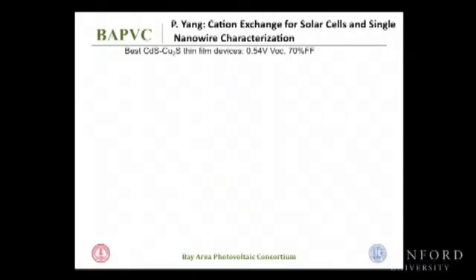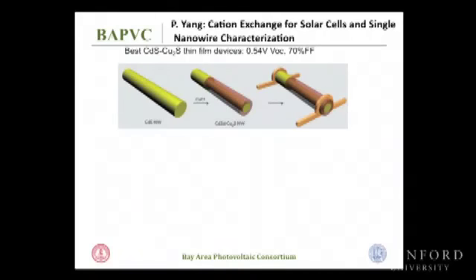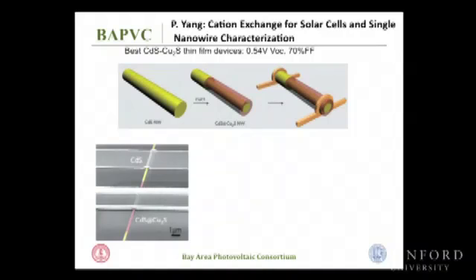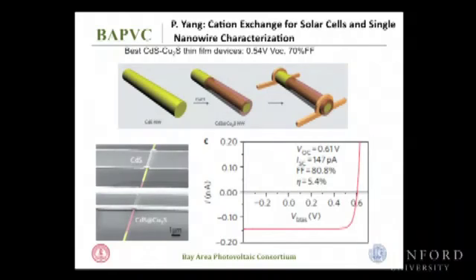Looking at the history, the best copper sulfide solar cell using cadmium sulfide to form the junction has an open circuit voltage of about 0.54 volt and a fill factor of 70%, and these parameters are just not attractive enough for solar cells. Through his research on nanowires, Peidong was making this cadmium sulfide using ion exchange, changing a segment of the nanowire into copper sulfide, now having a PN junction formation. It's not for manufacturing, but through this single nanostructure study forming these solar cells, he found something surprising.